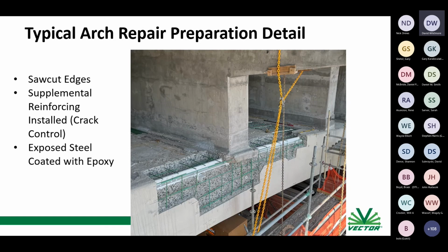One of the things that's being done here, and here you can see the typical saw cut repairs, the concrete removal's done, this concrete's been sandblasted, the exposed Melan steel has been sandblasted and coated white with an epoxy coating. That's to protect that surface so it's not drawing all the current from the galvanic anodes, because it's going to be in fresh concrete anyway. It's to force the current to go to the back side where it's not coated. So the white strips there are the Melan steel angles, in this case, that are partially exposed. And the green steel that you see is epoxy coated rebar that's been installed for crack control and doweling of the shotcrete repairs back into the substrate. Okay.